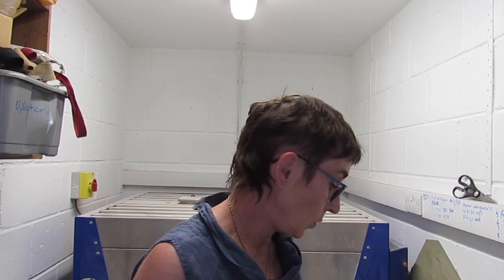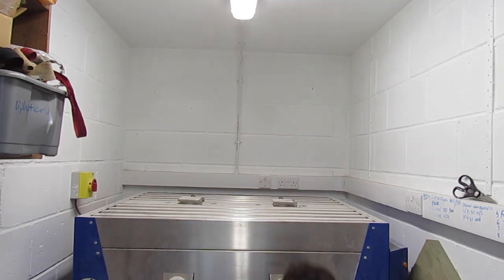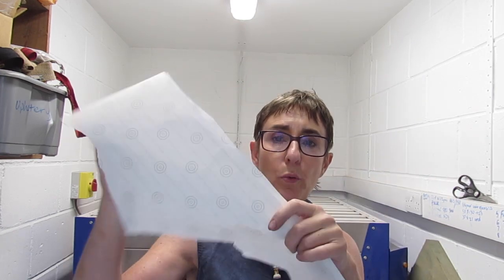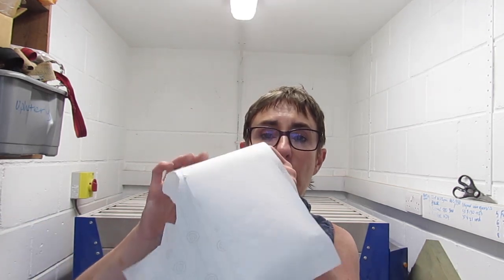What else can I tell you about kiln work? What do you put on your kiln shelf? You can't put your glass directly onto your kiln shelf. It will stick. I like to use this. It's kiln paper. It turns to dust when it's fired. And if you put one of these sheets on your kiln shelf every time you fire, in the end you'll get a nice thick layer of kind of dust. And then you don't have to keep using this. Your glass can sit directly on the dust.